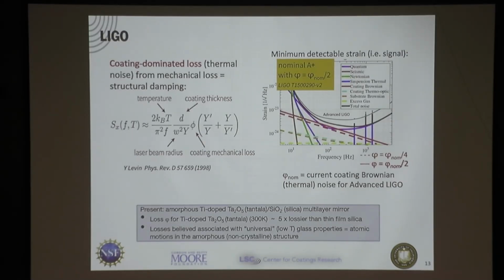And you get something similar in thermal conductivity and mechanical losses. Lots of other properties have what are called anomalous glassy properties at low temperatures. And one of the breakthrough papers back in the 80s, mostly attributed to Bobby Pohl at Cornell, is that they all look the same. So this is a universal property that glasses have, this low temperature linear term in their heat capacity and corresponding other such properties. That is found in the mechanical loss as well. So let me now show you the next slide.